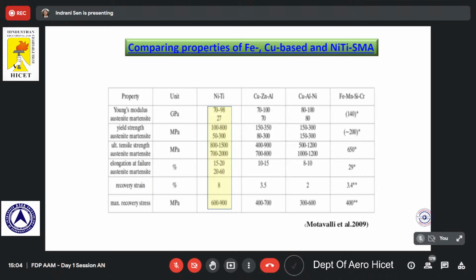Apart from that, it also has the elastic modulus, which is quite in the range of around 70 to 100. So that is what we can see for mostly all of the material. Most interestingly, what we can see here is that the martensite phase is having the elastic modulus, which is quite similar to that of human bone. And of all the applications of nickel titanium as biomedical applications, one of the reasons that nickel titanium is very much popular is because of its low elastic modulus in the martensite phase, whereas the other alloys, you can see that these are having quite higher modulus of elasticity even in the martensite condition.